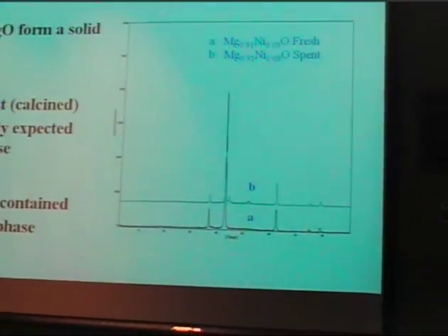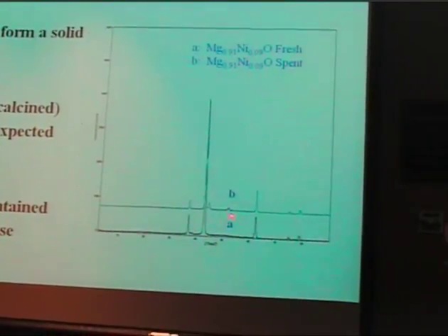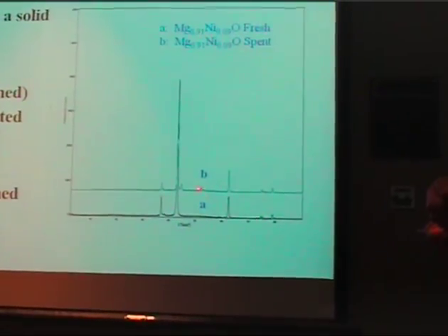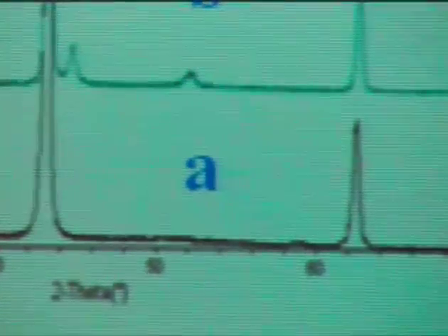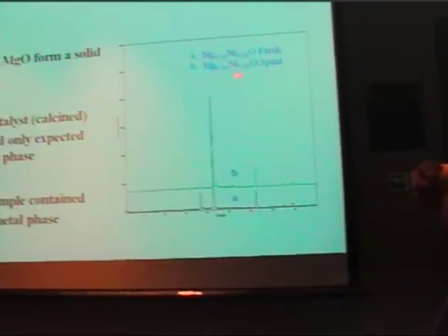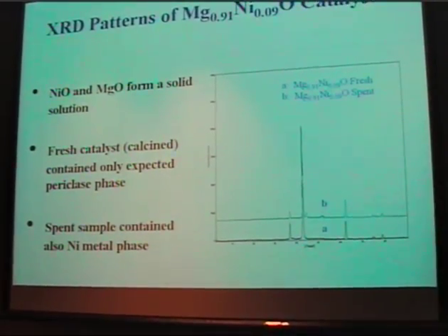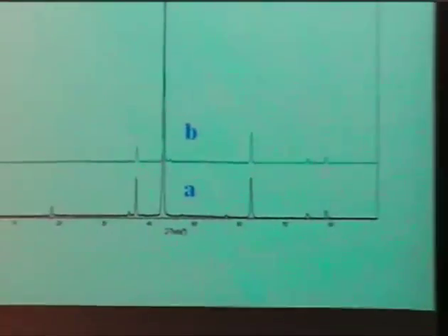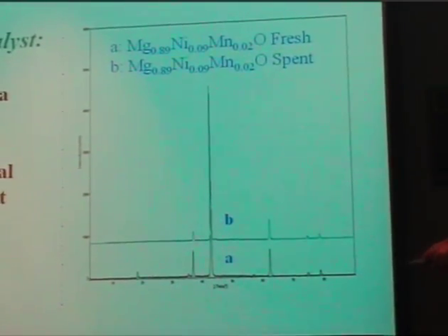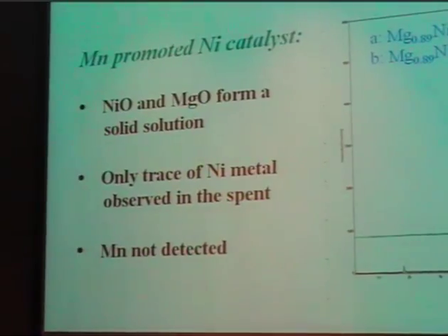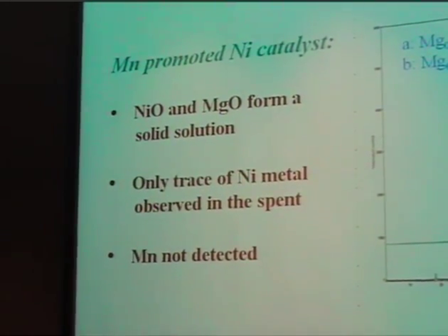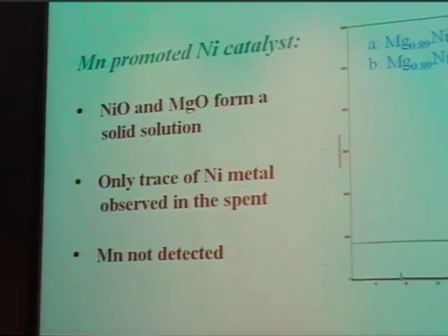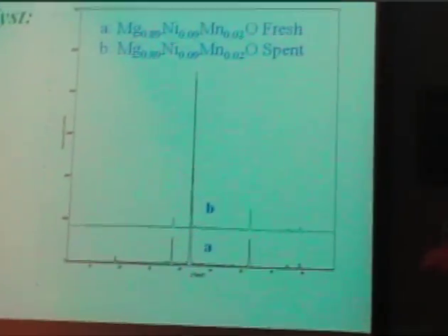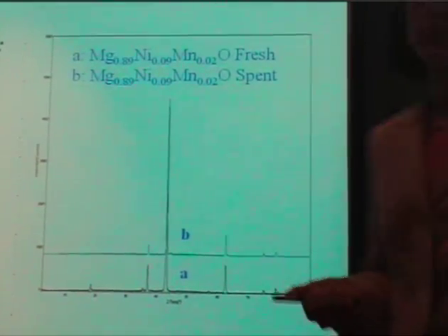So we only see the Periclase phase for the fresh, A. Now the spent catalyst, 2 theta angle roughly at 52, you can see a little bit of the nickel metal coming in, and this is without the promoter. And then shown here, we've now added the manganese at very low levels, and the manganese oxide also forms a solid solution in MgO. And we're seeing only maybe a very trace amount of the nickel metal showing up in the XRD. The manganese, you can't really detect any crystalline phase there.